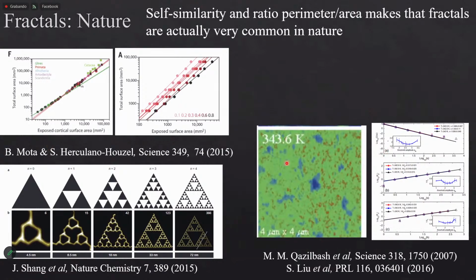And even for us in physics, if you look at a metal-insulator transition, you see things that have this self-similar behavior with a non-integer exponent that's basically related to a fractal. So this is a beautiful Science paper from 2007 looking at the metal-insulator transition, and this interpretation in terms of fractals was from 2016. So in some sense, when you have phase transitions, you have criticality, and criticality you can also associate with self-similarity. So you are hopeful that, okay, fractals are very common in nature, so if I go there and measure things, I'll be able to see fractals, right? But actually in materials it is not so common.